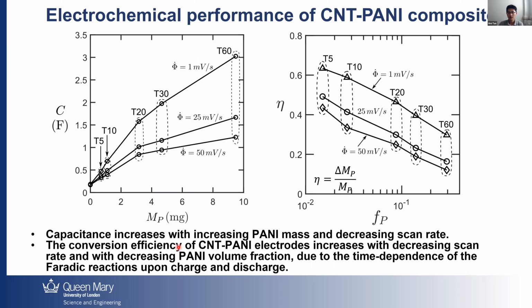The conversion efficiency here essentially means how much PANI is converted from one state to the other state. Due to the time dependency of these Faradaic reactions upon charge and discharge, the lower the scan rate, the longer time it has for the reaction. Therefore, the conversion efficiency is also higher, like showing here, these three lines. And the higher the volume fraction of PANI, the lower the conversion efficiency, because it's really just the thin layer of PANI in contact with the electrolyte that contributes to the reactions.